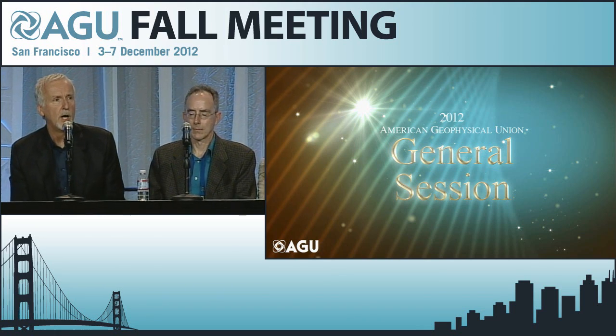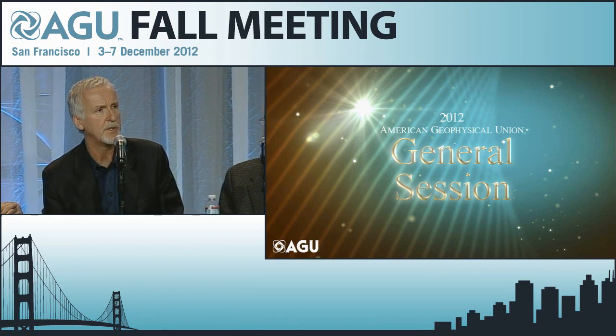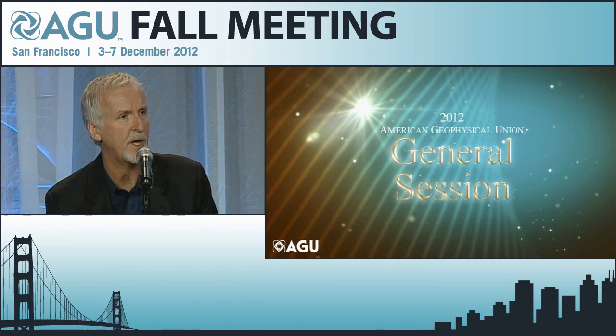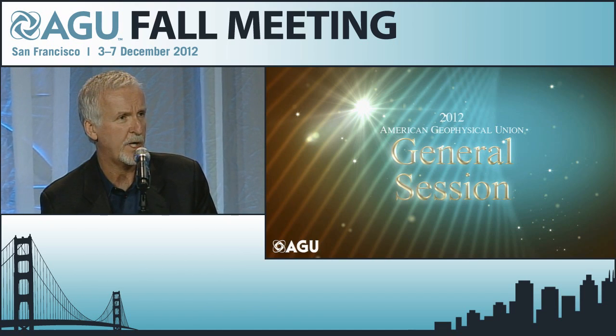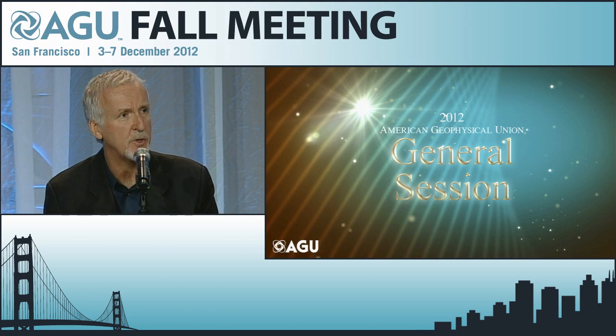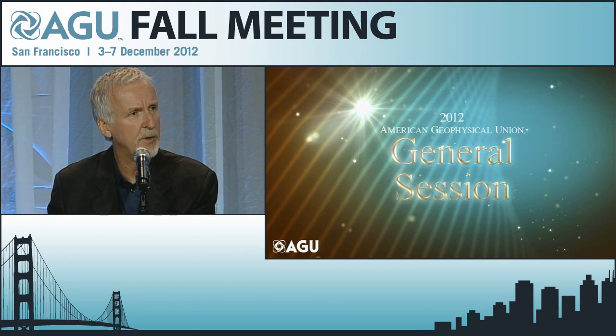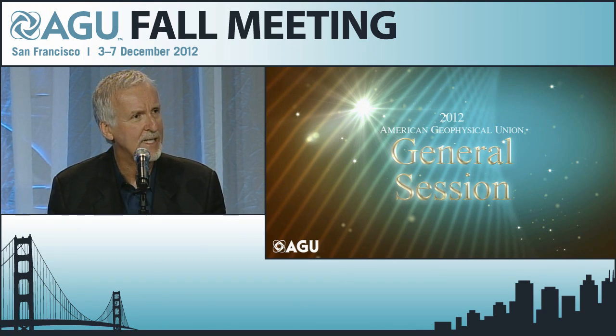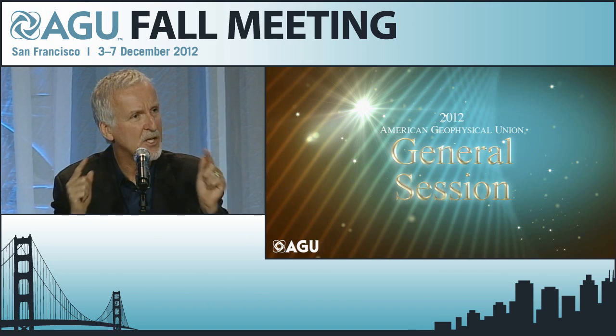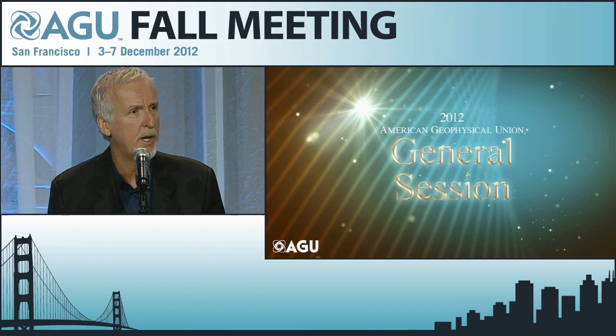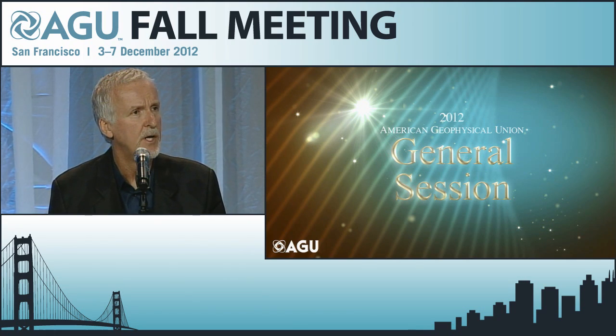Okay, so I'll do this here. We did extensive finite element analysis as we were making the sphere. And one of the advantages of working in the steel that we chose is that it could be machined after the forged hemispheres were welded together and after it was heat treated. So we did a kind of as-built FEA by doing a laser scan of the sphere, and we found some high spots and some slight out-of-roundness. We were actually able to take it down, and we did continued FEA as we took the sphere down. We were able to save weight and true it up for true concentricity around the whole thing.